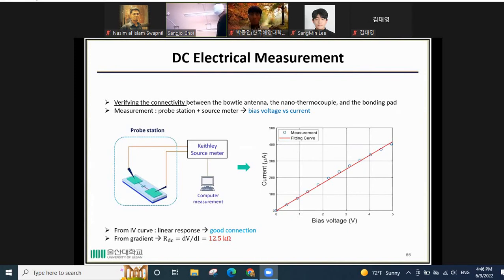And then we perform the measurement. First measurement is DC electrical measurement to verify the connectivity between the tiny nano antenna, nano thermocouple, and the bonding pads. So we use a probe station and source meter to measure the connectivity between those by using bias voltage and current. From this IV curve, you can see the linear response indicating a good connection between these three parts: bowtie antenna, nano-thermocouple, and bonding pad. And from the gradient of this plot, we can see that R_DC, that means the DC resistance of the device, is 12.5 kilo ohm.